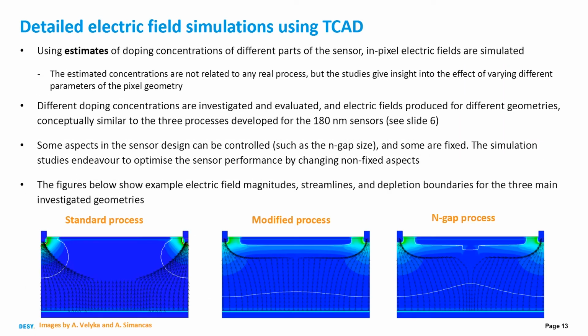So diving a bit more into this, TCAD, as I mentioned, is used to make detailed electric field simulations, and we use estimates of doping concentrations, not tied to a particular process, not 65 nanometer, not 180 nanometer, importantly, but we can still do relative measurements. So we try different doping concentrations in different parts of the sensor and create electric fields for different geometries conceptually similar to the processes developed for 180 nanometer that I showed back on slide 6. We can control some aspects of the design, such as the n-gap size, and some are fixed, so we try to find the best parameters with the ones we can vary, basically.